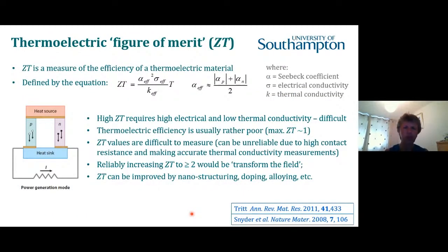I mentioned the thermoelectric efficiency is not quite as high as we would like it to be. If the efficiency was very high, these materials would have been in wide use long before now. The thermoelectric efficiency is normally measured or articulated in terms of this figure of merit term, which we call ZT. So ZT is defined by this equation here, and I don't want to spend too much time on it, but suffice to say it applies to some properties of the particular semiconductor material, which we can measure. We can measure the Seebeck coefficient, and then we've got a term here, which is the electrical conductivity. And on the denominator, we've got the thermal conductivity.